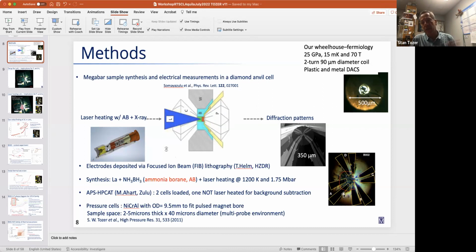You can see the sample here. We'll be seeing this micrograph a lot. The sample's smeared. It was a little too thick, and it's smeared off to one side of the culet. And we can see the issue with that is we sheared two of these leads because they didn't have any lanthanum on top of them.